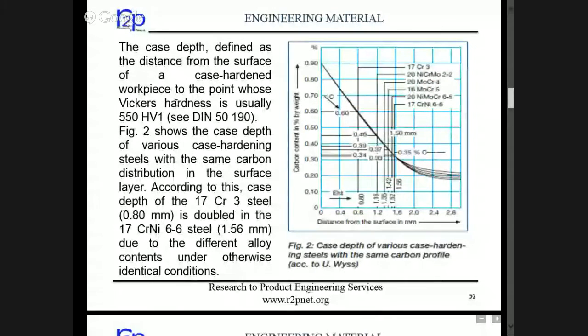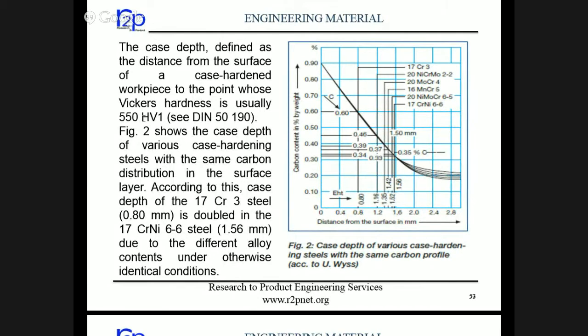What's case depth? At the surface, the hardness, like in a case hardened steel or gear or shaft, is around 58 to 63 HRC on the Rockwell scale. That's on the surface. But as you move 0.1, 0.2, 0.3, up to the case depth that we specify, we need a 550 HV hardness. So wherever 550 HV is achieved, that's the case depth. So it may be 0.8 mm, 1 mm, or 1.2 mm.